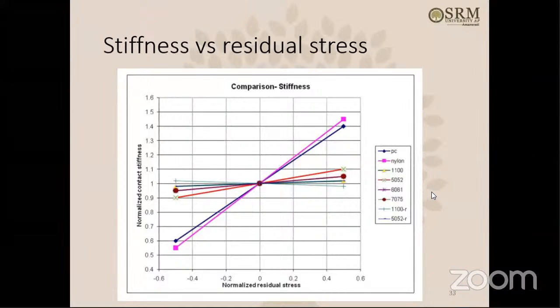Stiffness also varies, like you can see here for the polycarbonate and the nylon. The response is different as the residual stress varies in the material. For the softer materials like polycarbonate and nylon, the stiffness is going up. But for other materials, stiffness is almost constant, not very much. For some materials, it is still increasing like this.